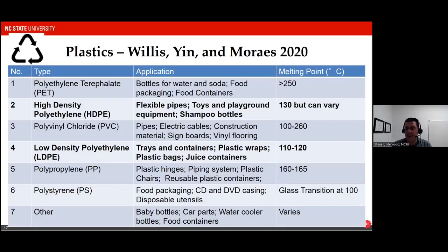And the reason for that difference has to do with a lot of factors, some technical. For example, one of the ways that we recycle these plastics is that we chop them up into very fine pieces and then heat them to a temperature to liquefy and then depolymerize, and we work from there. But for low density polyethylene, you can imagine a very thin plastic bag, it's very stretchy. And because of that, sometimes it's not easy to chop those bags up and incorporate them back into asphalt concrete. Or not in asphalt concrete, but back into the recycling process. So this low density polyethylene is a material that's actually used a lot, but is recycled very little. We only recycle about 6% of the low density polyethylene that we use.